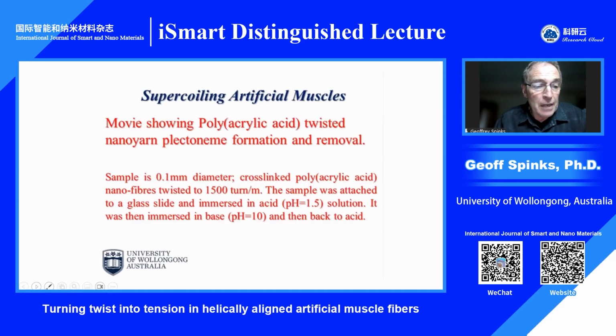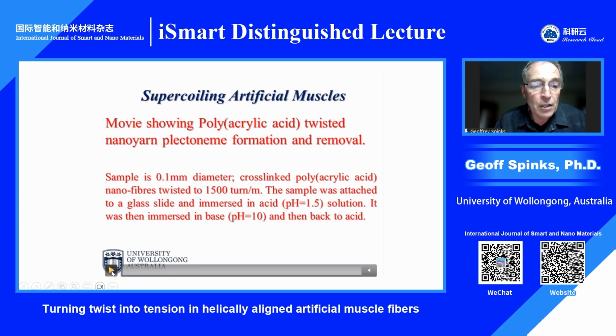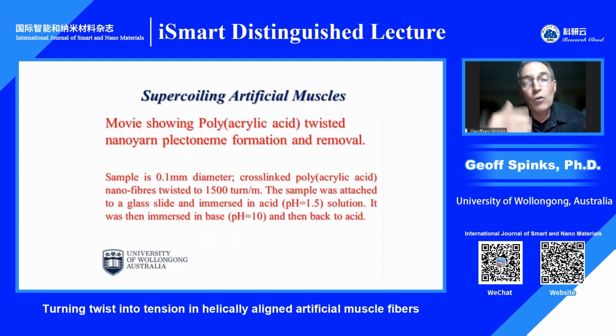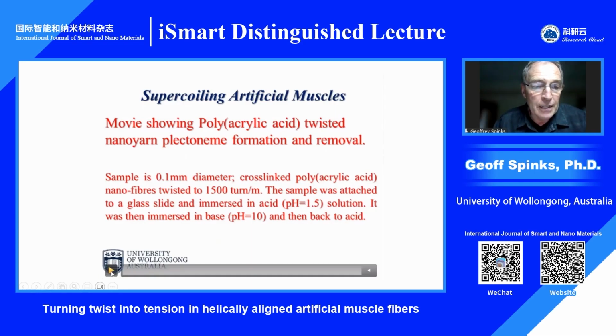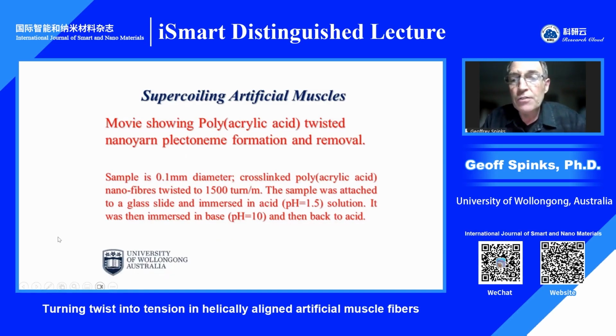Well, here's the first example of supercoiling in a macroscopic fiber that is not caused by inserting twist. This is a video taken by my student Niccolo Martino. He made electrospun polyacrylic acid fibers. He twisted them into yarn. He could swell those yarn in acid and base solution, and he knew that the free swelling caused untwist of the yarn. But in this example, he's tethered the ends of the yarn to a glass slide and then immersed it in acid and then in base. So this is what happens.